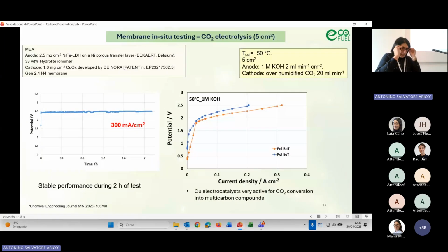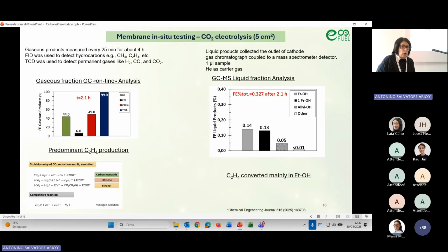In addition, this is just to show you the performance at the lab scale of the membrane H4. This test was carried out at the CNR lab with the nickel iron electrode produced by CNR and the cathode produced by DE NORA, and we can see a quite stable performance in a 2-hour test. The products are mainly hydrogen and ethylene, and of the liquid products that we collect, the most is ethanol.